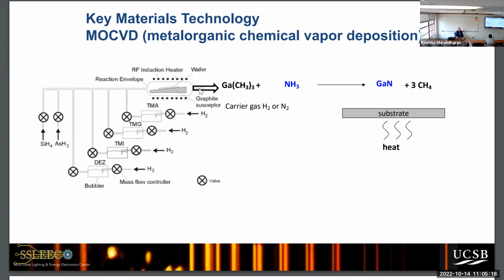And it's done at atmospheric pressure, so you don't even need low pressure. You can think of this as like spray painting gases at a very high temperature. You put in the metal organic compound, which is gallium with three methyl groups, hence the metal organic version of it. And you add just ammonia gas and you create a material which is not found in nature.